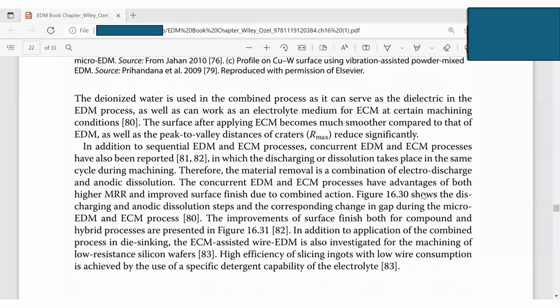This picture shows the discharging and anodic dissolution steps and the corresponding change in gap during the micro EDM and ECM processes. The improvements of surface finish for both compound and hybrid processes are presented in the next figure. In addition to the application of combined processes in slicing, ECM-assisted wire EDM is also investigated, and for the machining of low resistance silicon wafers, a high efficiency slicing technique with low wire consumption is achieved by the use of specific detergent capability of the electrolyte.